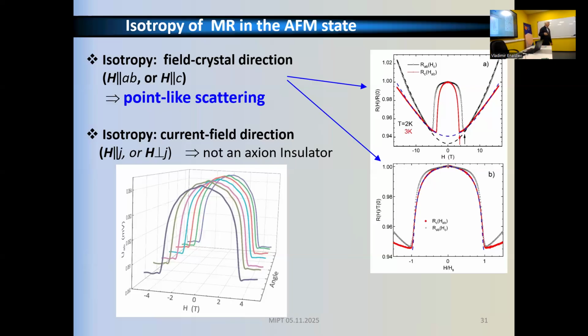Now, when it terminates, then it transforms to a parabolic rise, and this is a trivial effect because it's omega tau squared, which, were this a single band material, the magnetic resistance would be zero, but in fact, as we see this omega tau squared, it's experimental proof that we have a multi-band material. This is a semi-metal with at least two groups of electrons and holes. So this is not a puzzle. We take measurements of the Hall resistivity and diagonal magnetic resistivity, so we extract mobilities and scattering time, we put this in the textbook formula, and with no fitting parameters you get a nice agreement with what you see here.